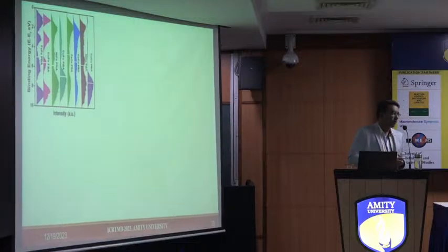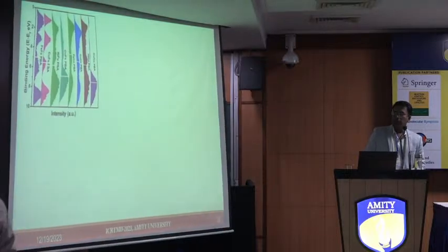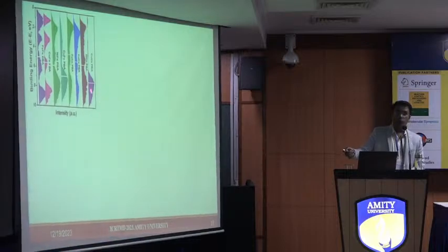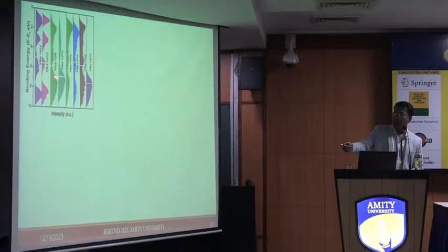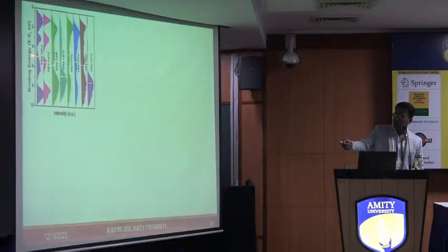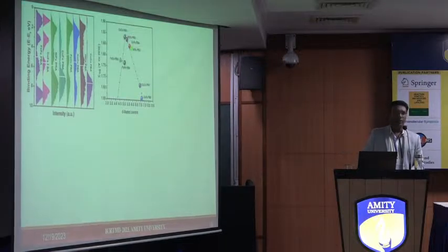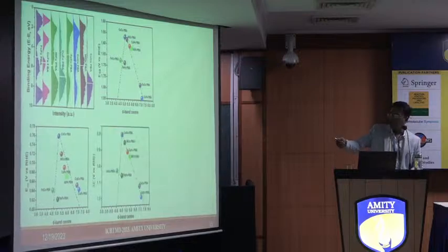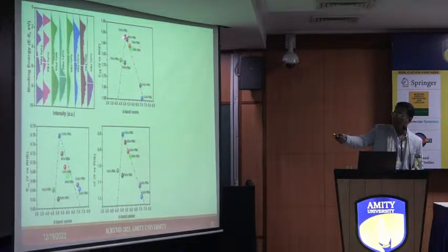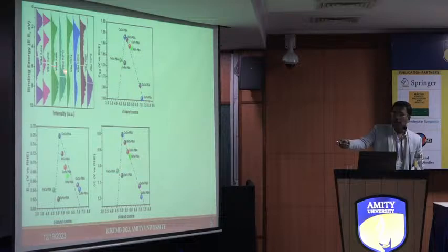Okay. Now, to correlate that, we measured the valence band XPS spectra. Valence band XPS gives you the measurement of the d band structure. Now you can look at the plot where we have calculated the average energy density of states. What you can see is that this d band center is actually moving, and the change in the d band center you can correlate directly with the activity. For example, the CoFe PBA is giving the highest activity, and in this d band structure, it lies somewhere here.